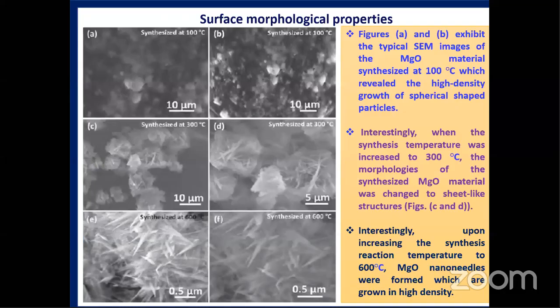And then this is also quite interesting. You can see how the surface morphology changes with respect to the synthesis temperature. At 100 degrees Celsius, look at the surface morphology of MgO. You can see it is highly dense. Why? Here the grains are highly agglomerated. That means surface energies are high, so agglomerations are high. At 100 degrees Celsius, we observe spherical shape morphology.